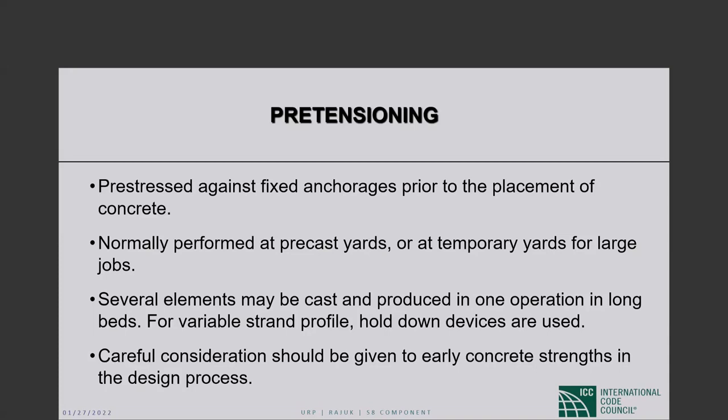So that property we call f'ci, the initial concrete strength, which could be quite a bit less than the 28-day strength. So if I design a structure where the stress is released at the early concrete strength, I must be careful to use that strength and not the design strength, which is down the line at 28 days or so. That's something very important, because otherwise there'll be a big mistake and our design will be non-conservative.